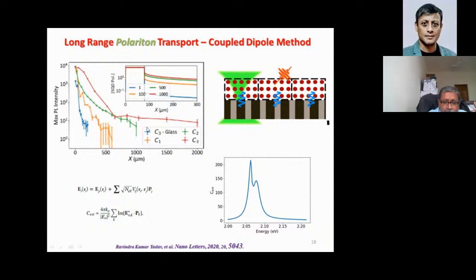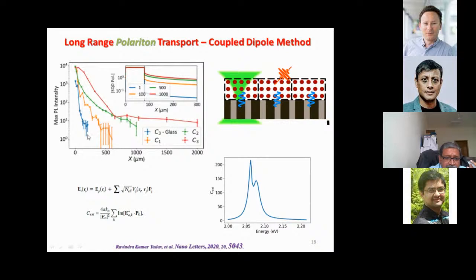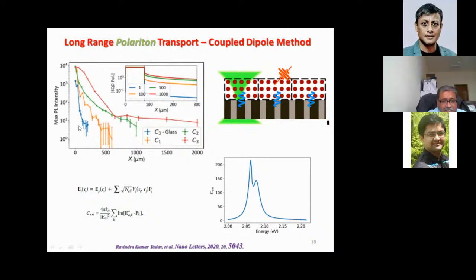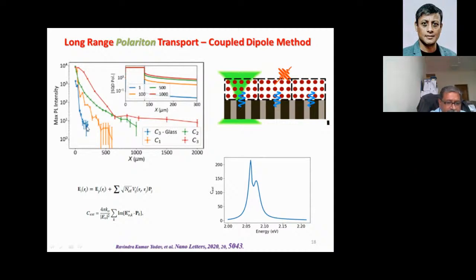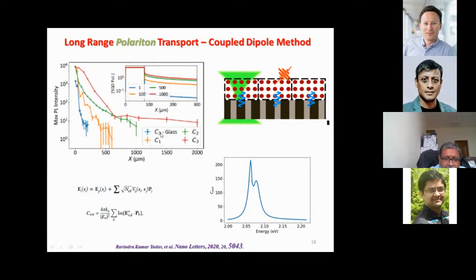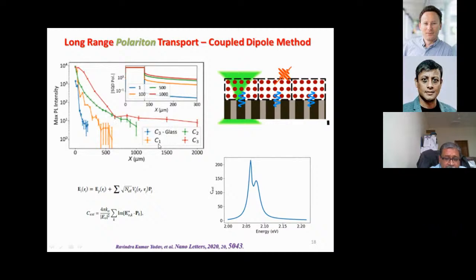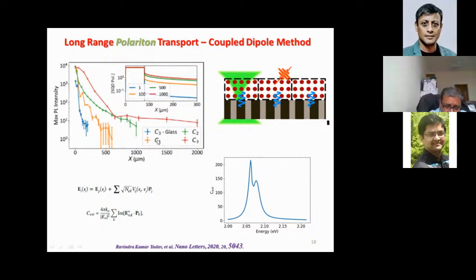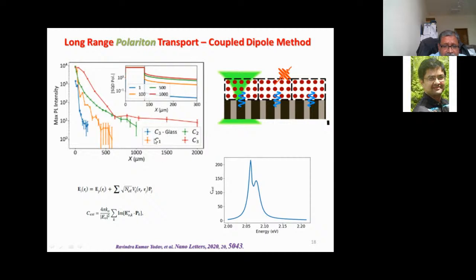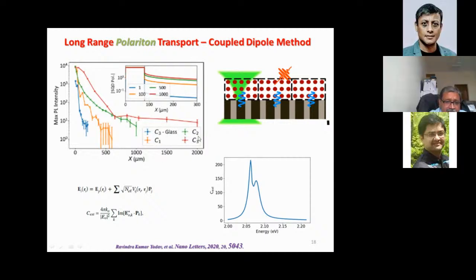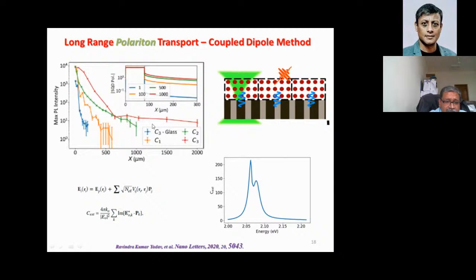So again, to complete the story, if you put this on glass, this just drops off abruptly, as you would expect, because there is nothing outside the excitation region. Exactly the same very compact, high density quantum dot layer, but it just decays close to the excitation regime. But when we look at these, you see that they are increasing, and not only that, the range up to which it propagates seems to be scaling with the concentration of the quantum dots. So this is the lowest one, and then this is slightly more, and this is more, and this keeps on increasing.